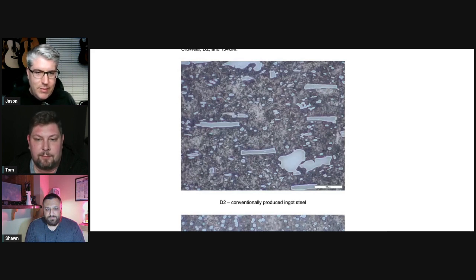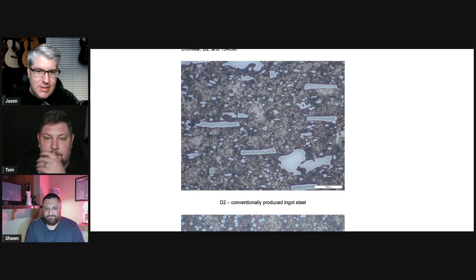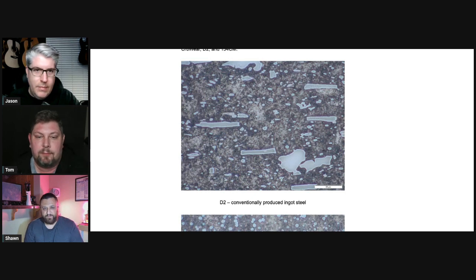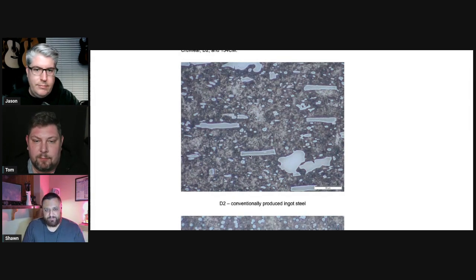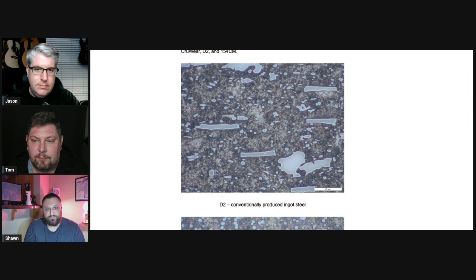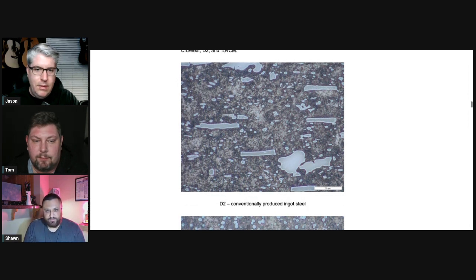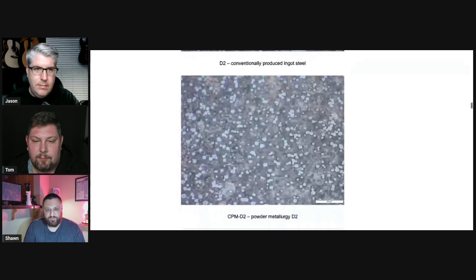In the case of D2, for example, we see these large carbides, just like Sean described. They're basically a much harder substance that's in the matrix of the steel. So as you described, the hardness is nice because hard stuff holds an edge better, but also they can be brittle. So the brittleness creates a problem where these things can crack and fracture inside the steel. Is that accurate? Yeah. These little white blobs you see, they're significantly stiffer than the tempered martensite and the matrix surrounding them. So it's a lot easier when enough energy is sent through them. They're more likely to crack when it goes past the yielding point versus with the tempered martensite. It'll have a little bit more ductility, plasticity to it versus the carbides.